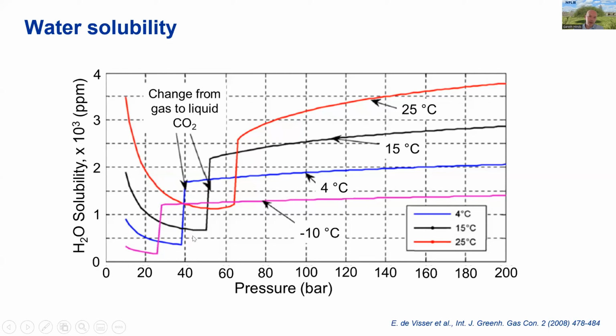And this means that, allowing for this, pipeline operators often have to set quite low levels for the water specification in the CO2 composition. And many operators set limits as low as 50 ppm to make sure that liquid water doesn't appear in the pipeline. Now, obviously, cleaning the CO2 up to that level brings additional cost. So anything that we can do to understand and mitigate the corrosion will really help with this cost.